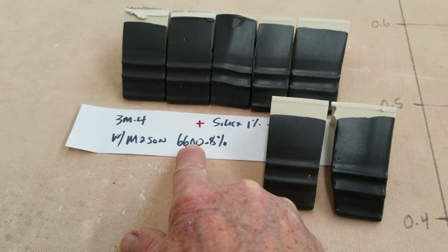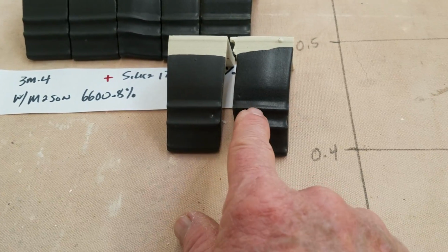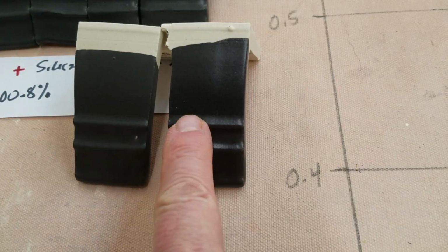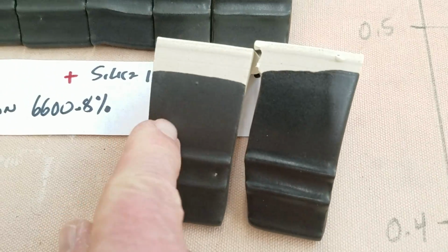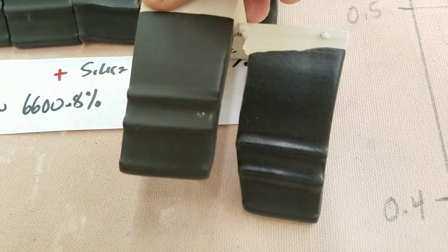So I wanted to have a black that was not completely matte, but satiny. So I kept adding silica. I believe it was 1%. And here are my final tiles. You can see how that's kind of glossy compared to how matte this one is. That's super, super matte. Okay, so you can go in there and pick wherever you think is good.